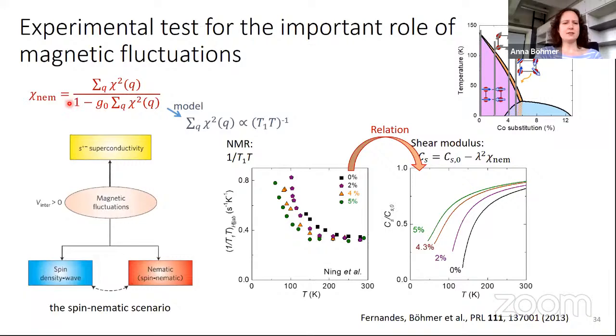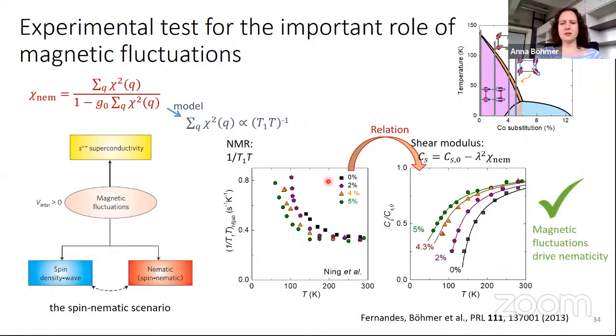On the other hand, this left-hand side I can measure as well. That was my shear modulus, my 3-point bending experiment. And the theorist can tell me that there should be a relation between these two. What we do is we test this relation and we scale the one data on the other, and we find this works. So that theory that starts with magnetic fluctuations driving nematicity works, can explain this data, and we found evidence for that. And we're quite proud.